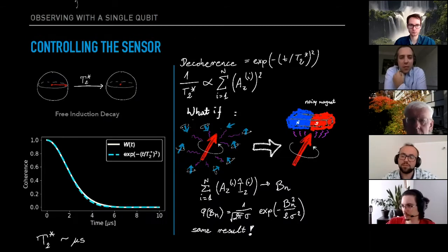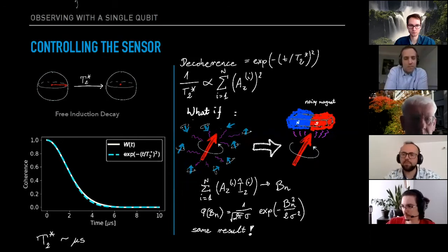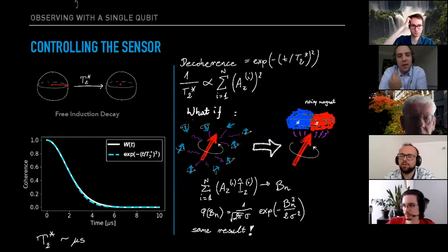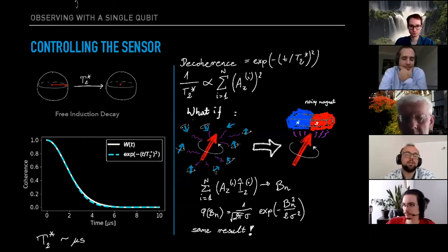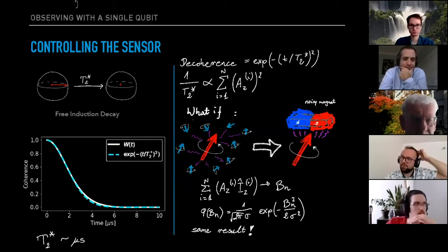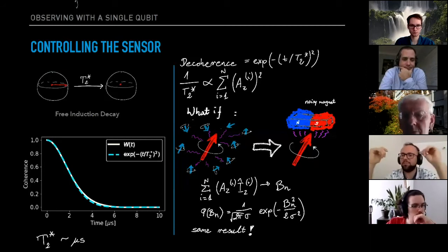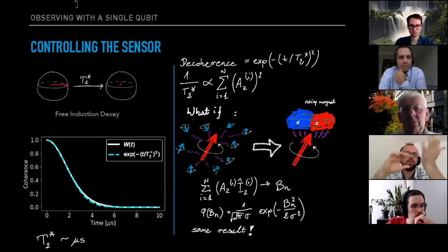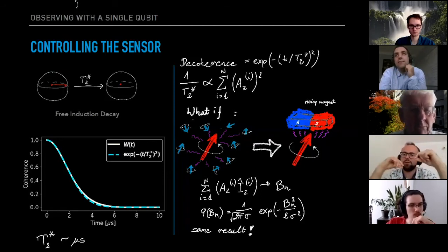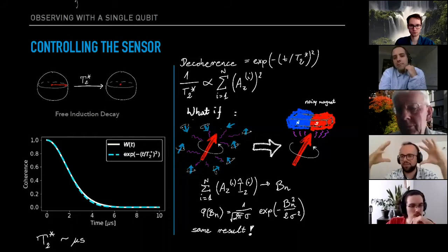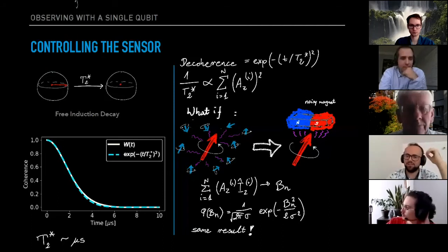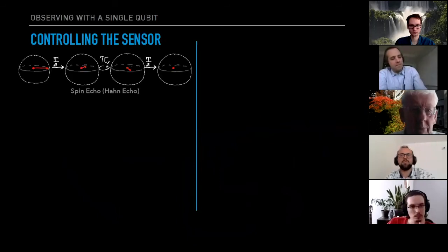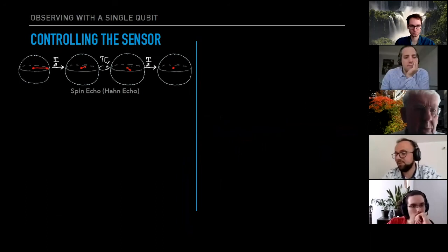Those parallel interactions depend on the distance of the C-13 carbons to your defect — so it's effectively an average of all of them. Dipolar interaction goes like one over r³, so it doesn't have a well-defined theoretical range, but there is an effective size of the environment that I will elaborate on later.